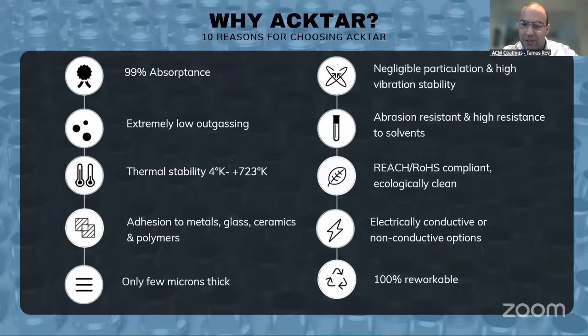In terms of abrasion resistance, we have variability, from light to medium to moderate, moderate plus. But generally speaking, they are resistant to solvents. Any traditional solvent like IPA, acetone, ethanol, you can gently wipe, clean, rinse, even ultrasonic cleaning is fine. Our technology and our coatings are REACH and RoHS compliant, and the processes are ecologically clean. We can also tailor the coating's surface resistivity. Generally speaking, we are in the static dissipative range, but we can tailor it to be less or more conductive on either end of that range. And if you're not satisfied with the outcome, we can take off the coating and put it back on.